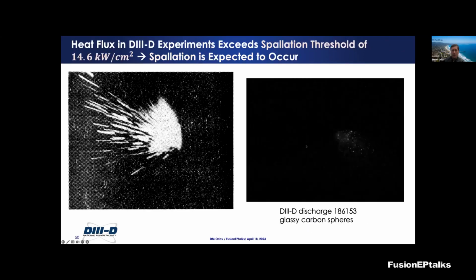Interestingly, when we were launching the glassy carbon spheres, we saw a lot of different sparks and shards flying around, and this is the indication of the spallation process happening on the surface of those glassy carbon spheres. Once that spallation removed a bunch of glassy material from the surface of the pellets, you could see the nice little spheres flying further into the plasma, with normal ablation happening from there.